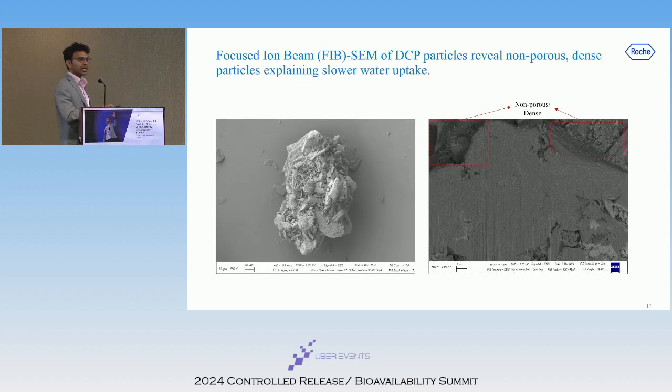So we wanted to explore if there is any other imaging technique that can help us visualize these and gain these micro insights of these tablets. So we leveraged another technique called focused ion beam scanning electron microscopy. This is similar to conventional SEM. However, it differs in that for conventional SEM, we use an electron beam for imaging, whereas here an ion beam is used, typically gallium, which results in a very high resolution picture that can resolve nanoscale microstructures.